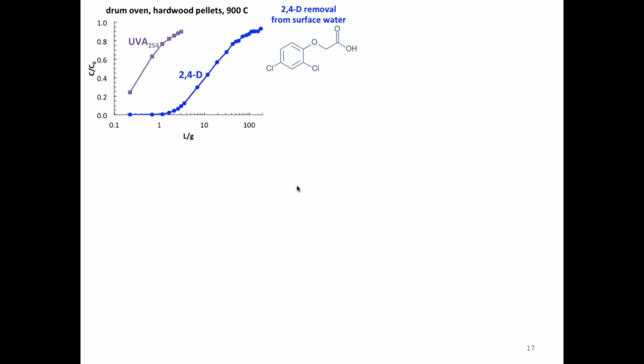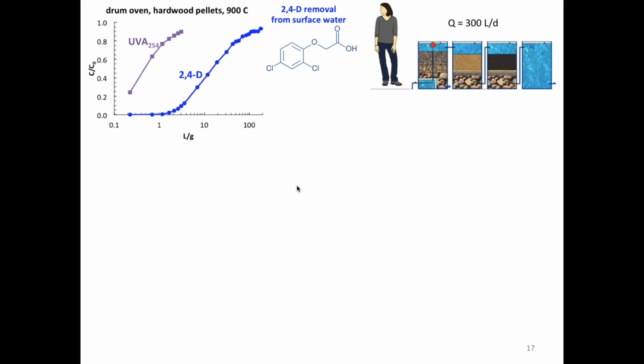So the idea with tracking UV absorbance of the background solution is it could give us potentially a conservative tracer or proxy for the bed life of the char. And so we measure that in the lab along with our experiments measuring pollutants, and we can also measure that in the field and use it as a sort of reality check on how well things are actually working in the field. So here's one example breakthrough curve for the small 300 liter per day system.